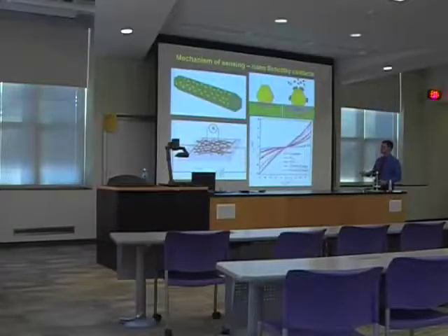So the top curve is the result under vacuum when we don't have any environment in the gas chamber. Then we inject hydrogen and see a drop of conductivity. Not a big drop, but definitely a reduction. Then pure CO. Pure CO affects it more significantly.